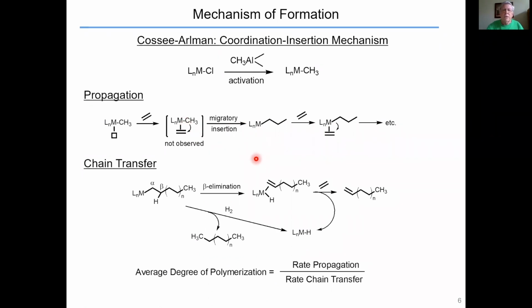The molecular weight in these systems is often limited by chain transfer processes, and the most common one is chain transfer through beta elimination. So as the chain grows, the beta hydrogen can be transferred to the metal to generate an olefin hydride. This unsaturated chain drops off. The metal hydride starts a new chain. The other way we can do chain transfer is through hydrogenolysis. So we expose this system to hydrogen, we can clip off the chain and make a metal hydride and start a new chain. So the average degree of polymerization is simply the rate of propagation over the rate of chain transfer.